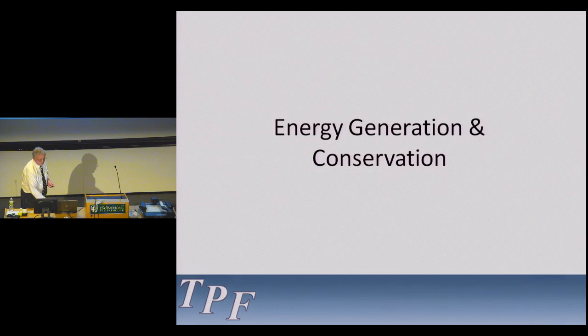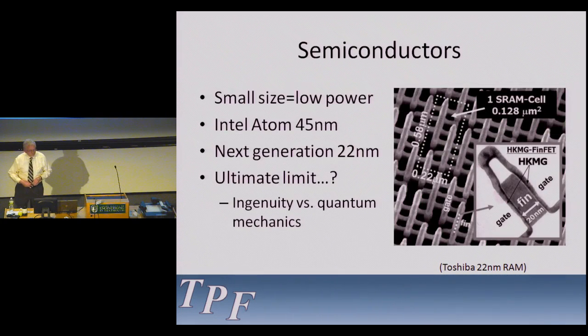So let's talk about energy generation and conservation. Well, with small size in electronics comes low power. So until you reach a limit, and that limit seems to be about 10 nanometers, the smaller you make electronic devices, the less power they use. And this is a 22 nanometer RAM from Toshiba. Intel Atom that goes in a lot of netbooks, that's at 45 nanometer. The next generation's 22 nanometer. We'll probably see one generation more in semiconductors.